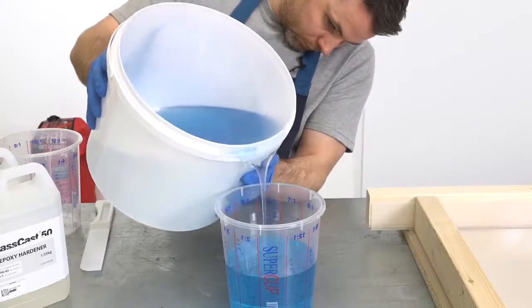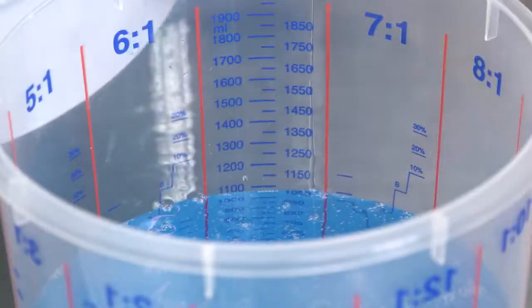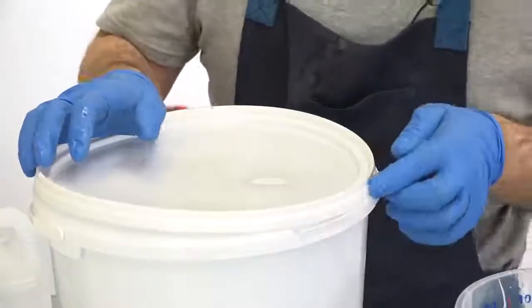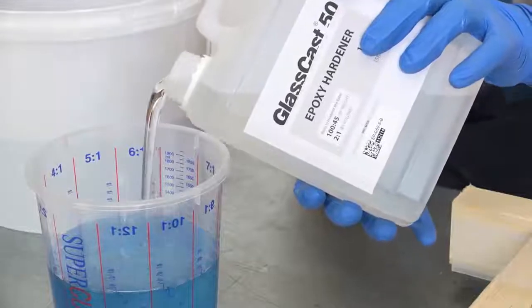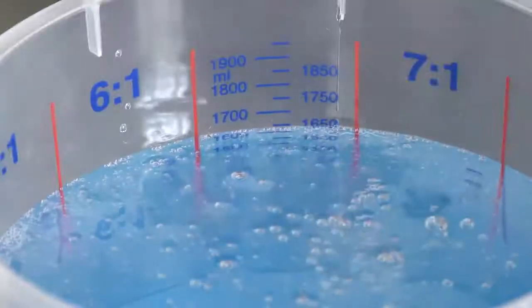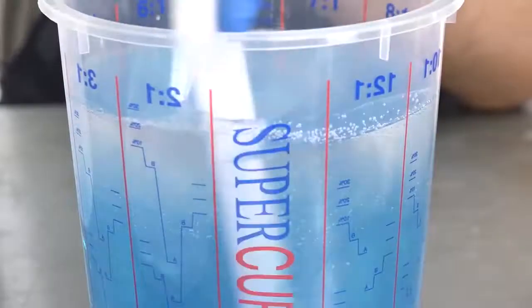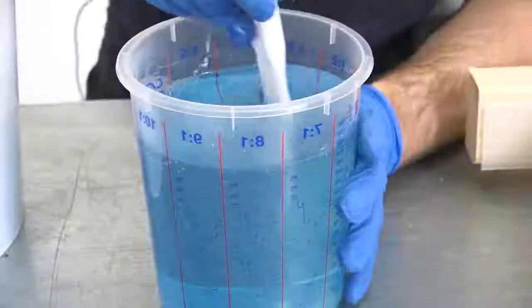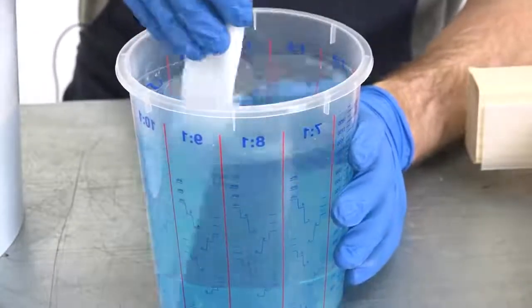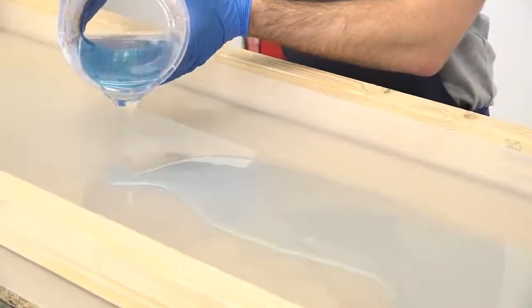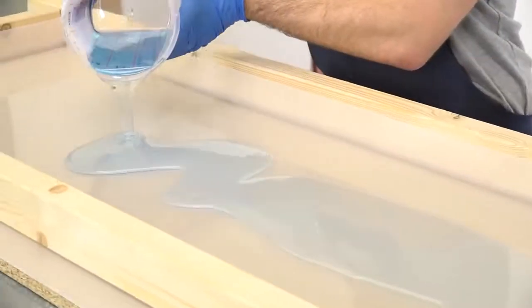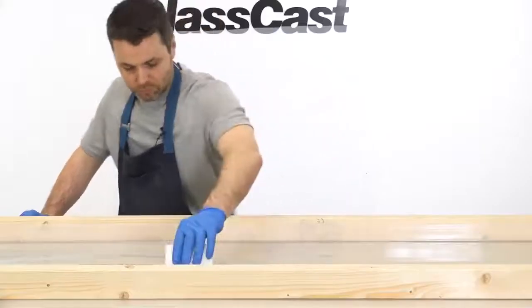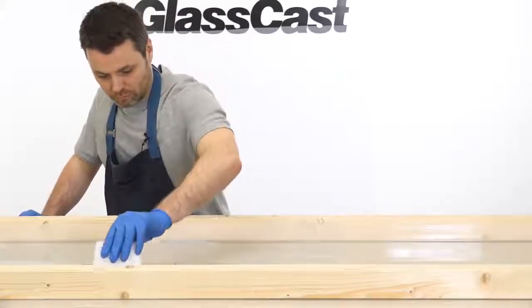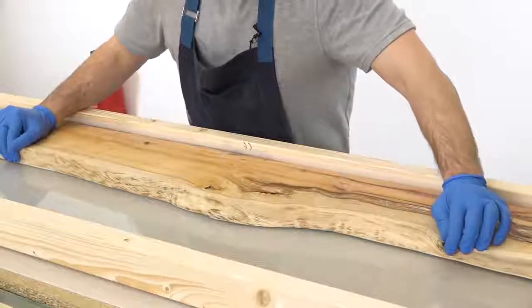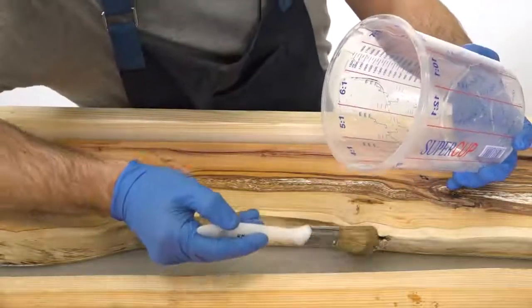With all of the resin tinted, I'll measure out the correct ratio of resin and hardener to make up the 1.6 kilogram quantity that we calculated earlier for the sealing coat. And we'll carry on using the double potting procedure to ensure that no unmixed resin finds its way into our table. By pouring the resin onto the base first, we can ensure that a full sealing coat of resin is underneath the wood, avoiding the risk of air pockets under the planks escaping during the cure.